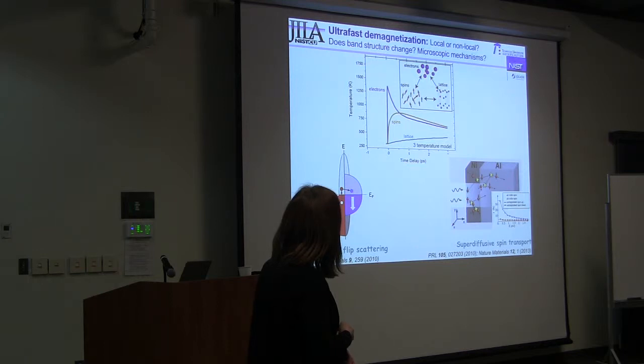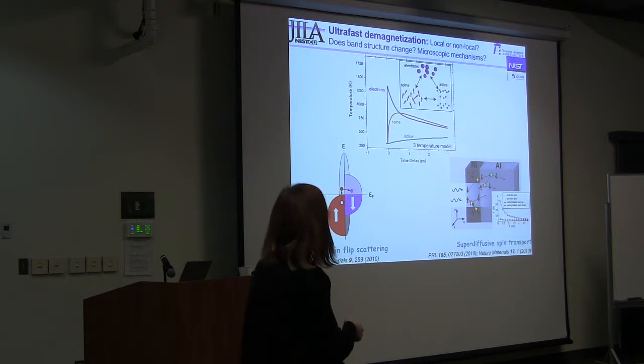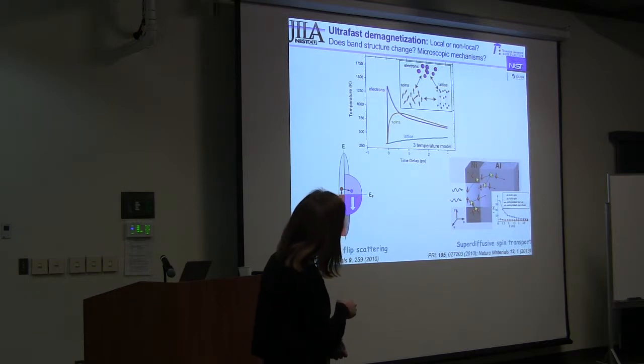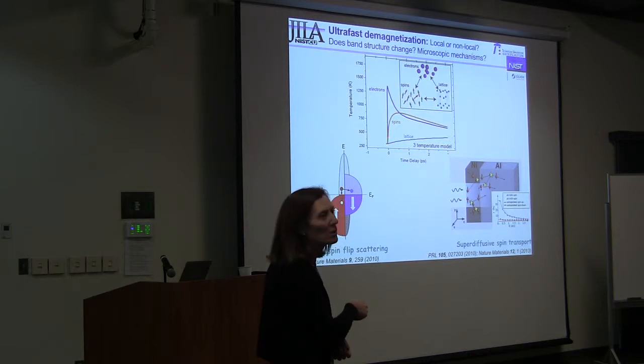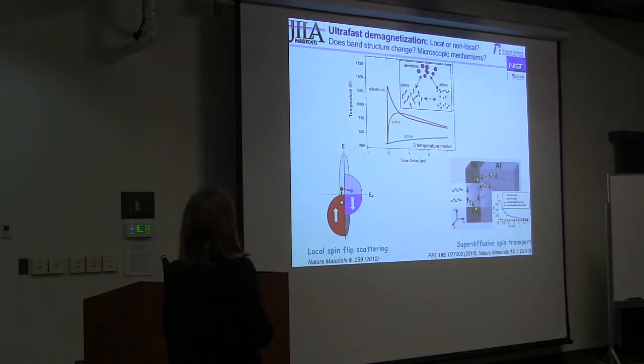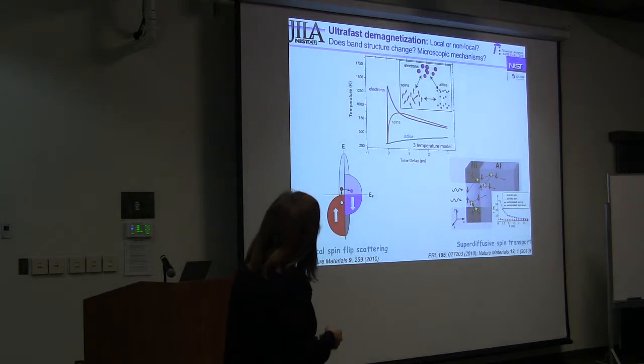But to make a long story short, this is the phenomenological 3-temperature model that I told you about. If you notice here, after the femtosecond laser pulse, your electron temperature spikes up to well above the Curie temperature in a normal ferromagnet, because their heat capacity is so much lower. Then coupling to the lattice will very slowly heat the lattice, but the lattice stays well below melting. And the spin temperature is a little bit phenomenological, but microscopically.